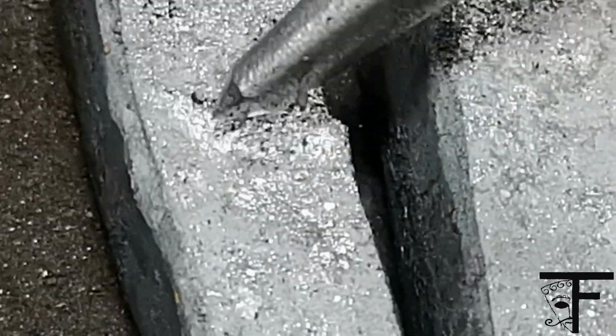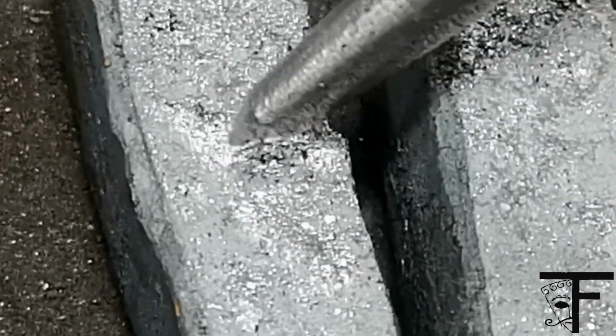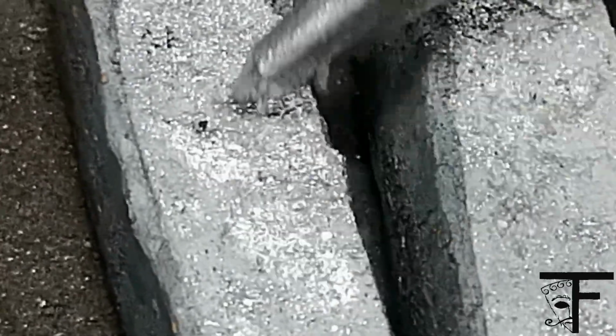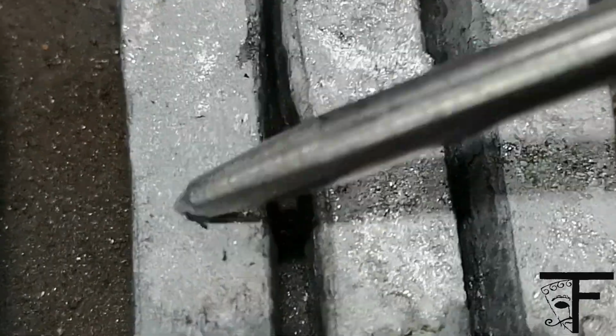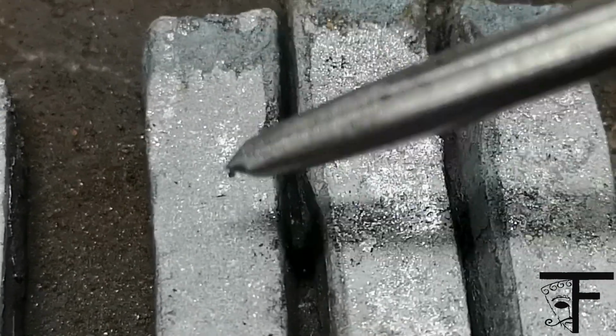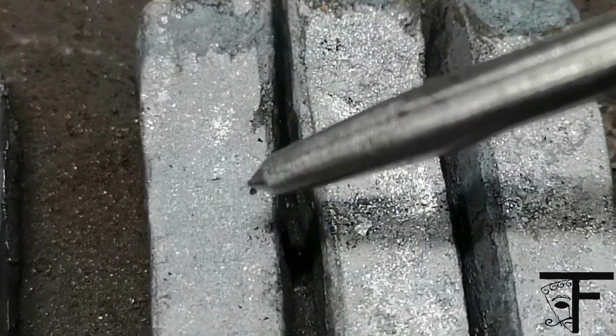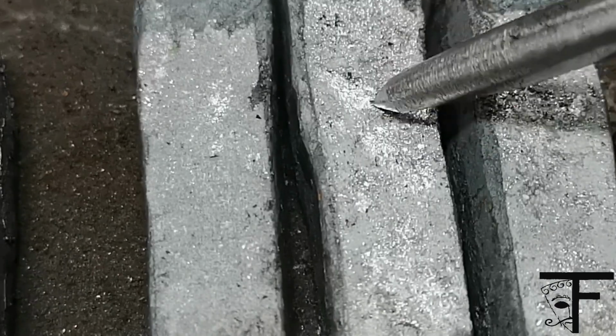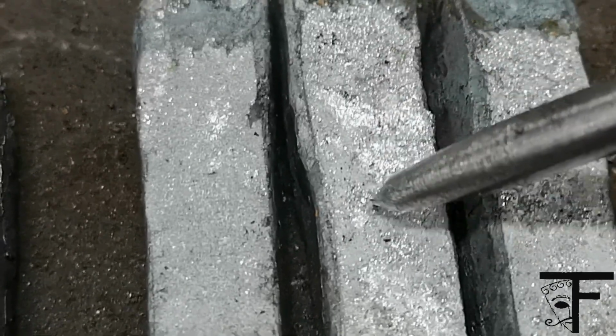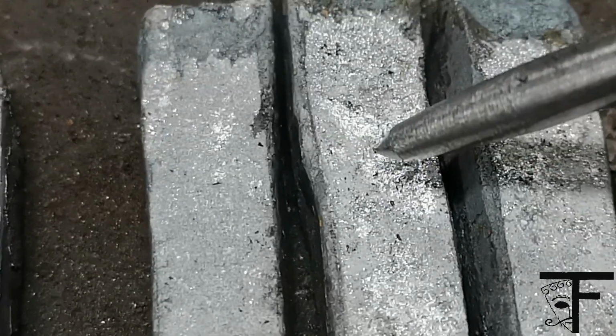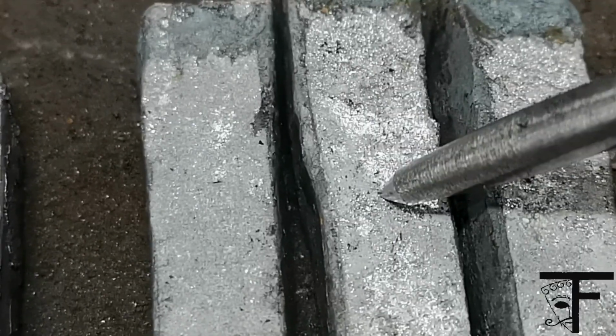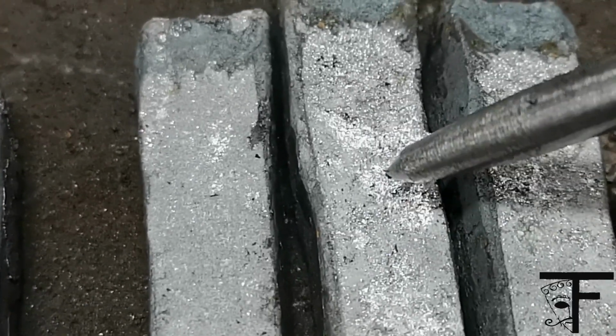You can see this one, which is fine grain, is an okay weld, but what we would like to have is this grain structure. Very good weld. You can see it's more shiny and there's more texture on it. Both of them are good, but for this one to reach this, you have to soak more in the heat and let it get more melted. And that is the reason why they get more texture and why it's a bigger diffuse line, because it has longer time to be melted and longer time to fuse together.